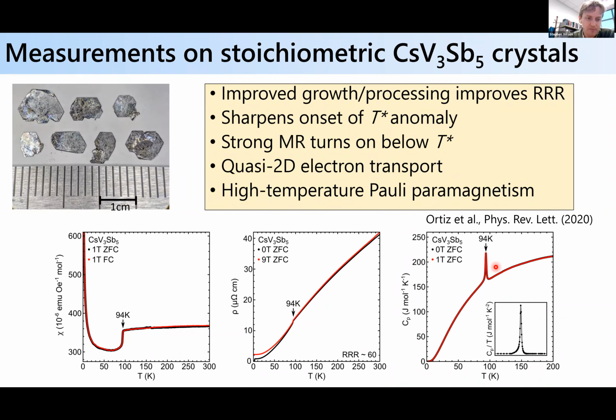Yeah, that's a good question. I think initially our picture of that was that there were some impurity moments somewhere in the sample, very weak. If you calculate the fraction of free impurity moments it would be, it'd be very small. However, as I'll present later, there are pictures that potentially time reversal symmetry is broken below this charge density wave transition at 94 Kelvin, and it's potentially somehow related to that. We're investigating that now. I think there's more structure to that low temperature susceptibility that you see there when we looked a bit more carefully, but that's ongoing. I can't say anything too sharp about that yet.